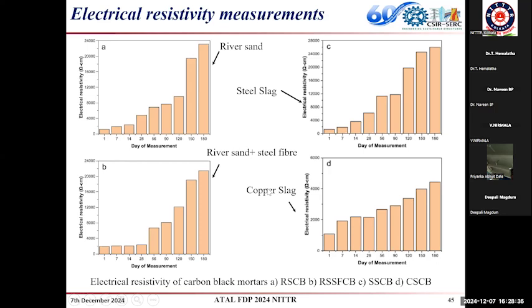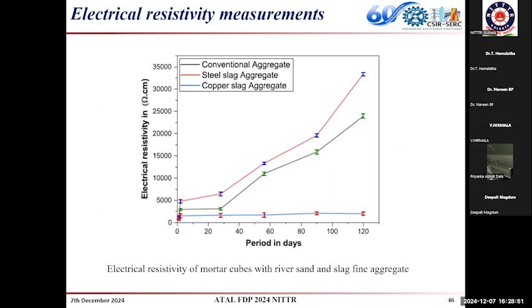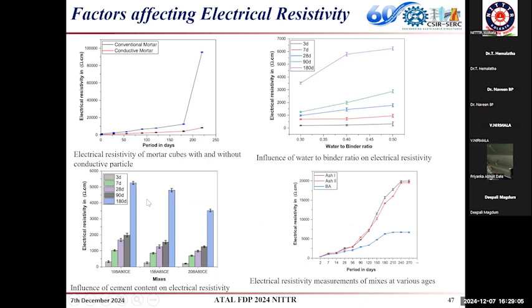So for developing this kind of special concrete, this copper slag is a good ingredient. Based on that, we have used this copper slag as a fine aggregate in this particular type of concrete. And this again shows that when we use 3 different types of aggregates, copper slag has the low electrical resistivity. And this shows the electrical resistivity of mortar cubes with and without conductive particles.